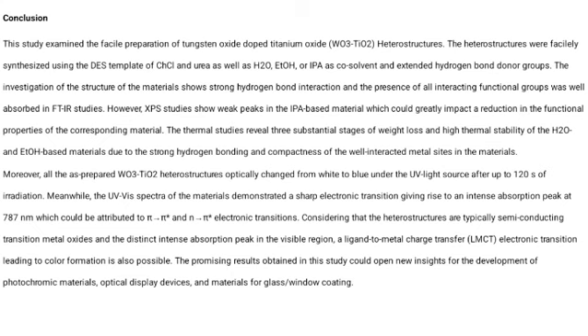However, the XPS studies show a weak peak in the IPA, which is the isopropyl alcohol-based material, which could greatly impact the reduction in the functional properties of the corresponding material. The thermal studies revealed 3 substantial stages of weight loss and high thermal stability of the water and ethanol-based materials due to strong hydrogen bonding and compactness of the well-interacted metal sites in the material.